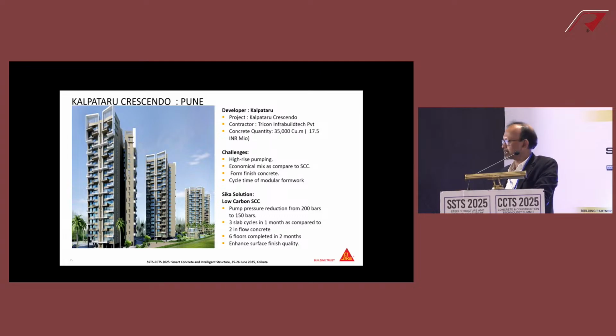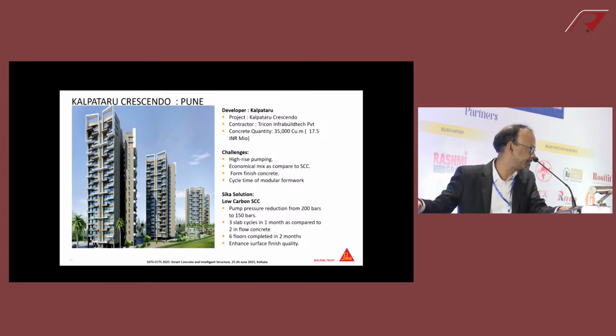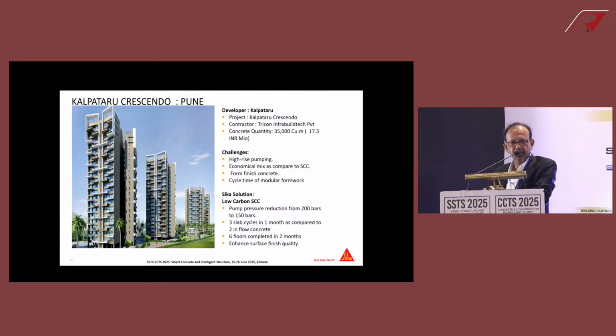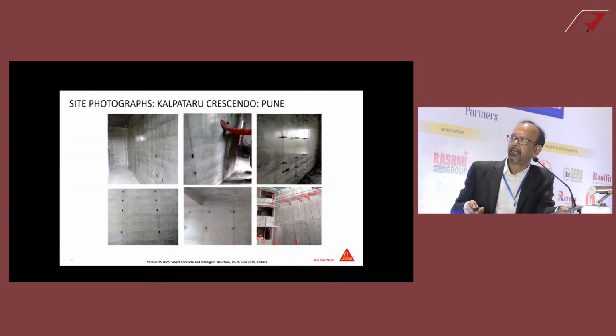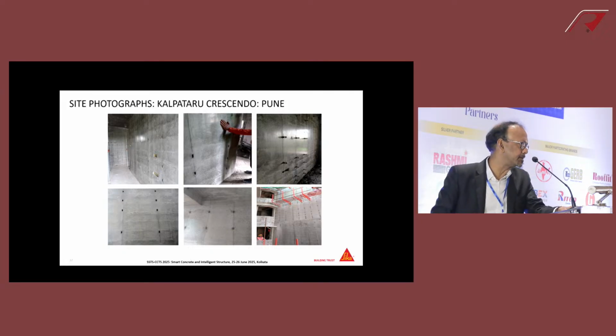So the other advantage was pump pressure. Now if you've got a very stiff mix, which cannot be pumped but looks very flowable, so when you lift your slump cone, it will creep on the slump board. Now for that you require a high pump pressure. So if you're pumping 50 meters, 100 meters, you will require 200 or 250 bar. You see the reduction by 30% to 150 bar. That means less wear and tear. Less consumption of fuel by the pump, which is also CO2 savings. So if you look at the total cost optimization, using such low carbon SCC is always beneficial. I told you, of course, I cannot see my face on this, but look at the fair face.